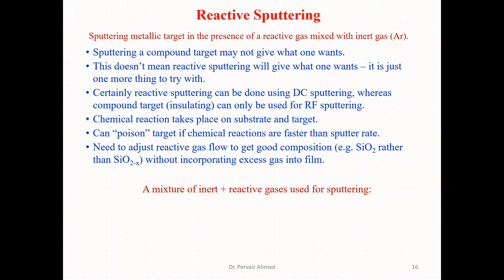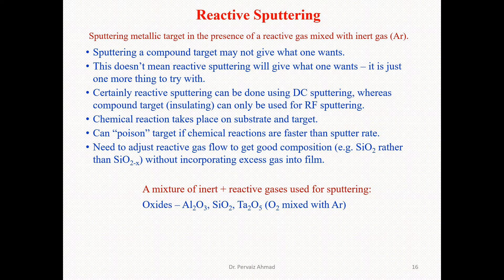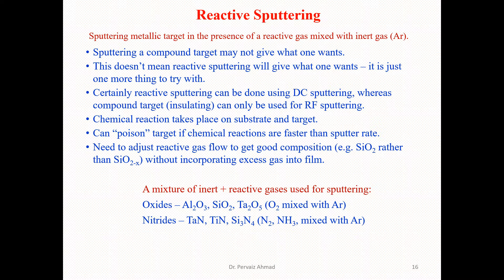Typical reactions use a mixture of argon plus reactive gases for sputtering. Practical examples include: for oxides — aluminum oxide (Al2O3), silicon dioxide (SiO2), or tantalum oxide — oxygen molecules mixed with argon are used. For nitrides — tantalum nitride, titanium nitride, silicon nitride — the reactive gases used along with argon include nitrogen and ammonia mixed with argon.